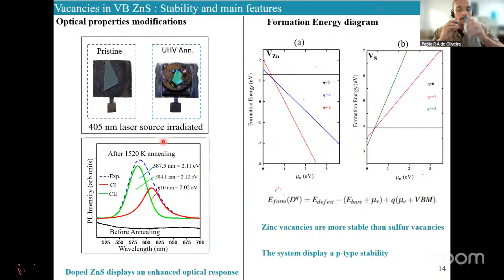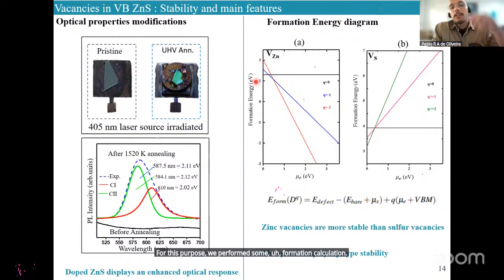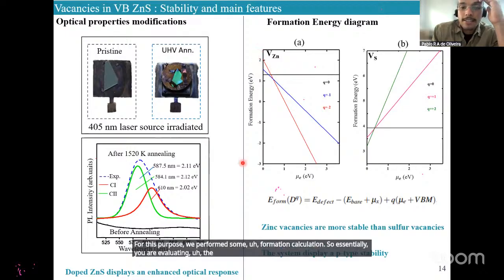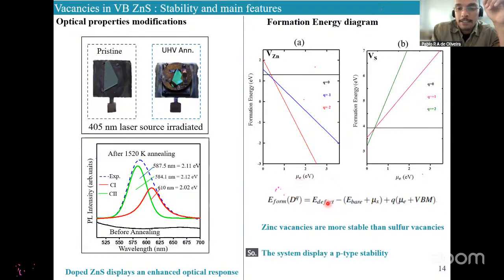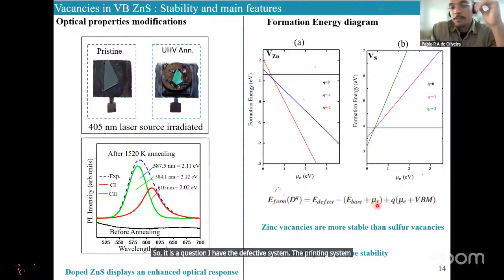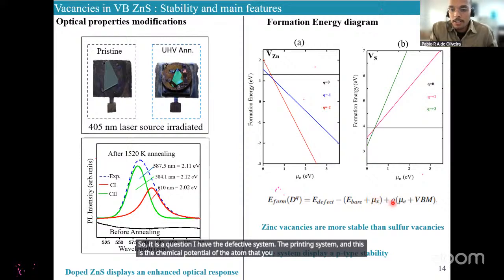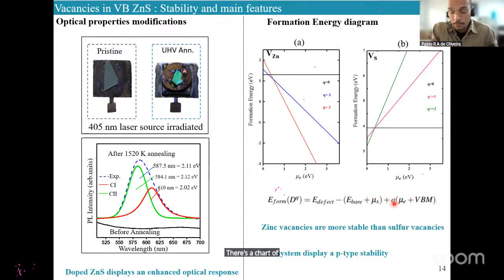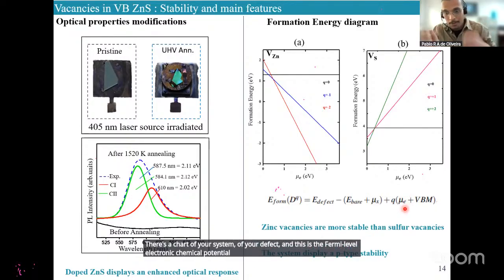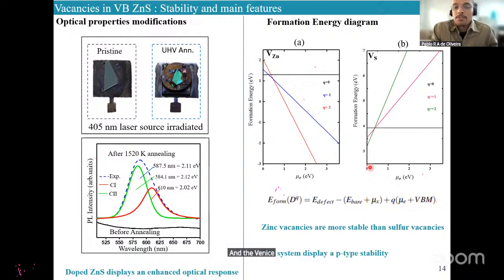For this purpose, we performed some formation energy calculations. So essentially, you are evaluating the formation energy of defects as a function of the electronic chemical potential. In this equation, I have the defective system, the pristine system, and this is the chemical potential of the atom that you remove. This is the charge of your defect, and this is the Fermi level, the electronic chemical potential, as I used to call it. The valence band maximum is usually shifted to 0, and spans from 0 to the band gap.